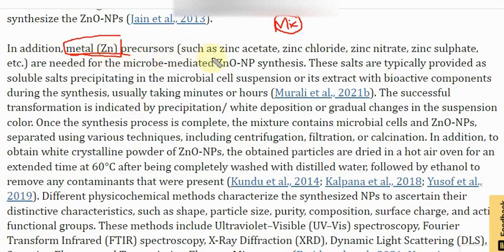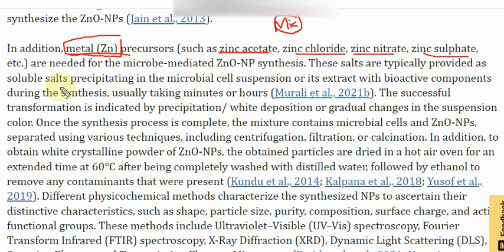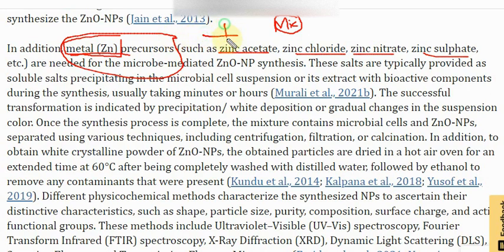Zinc has multiple salts available: you can use zinc acetate, zinc chloride, zinc nitrate, or zinc sulfate — any metallic salt which gives us the metal ion when dissolved in water or another solvent. After selecting this salt, you form a solution and then mix this salt solution with the microbes. The already-selected microbes then try to reduce these metallic ions into metal or metal nanoparticles.